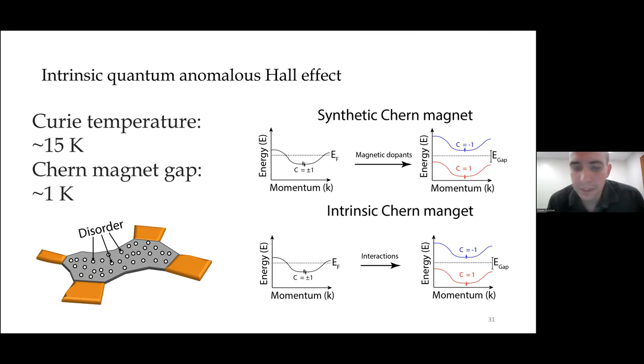And in particular, these doped TIs had the opposite limit from the one I just described. They had a situation in which the Curie temperature was very high, indicating that magnetism was very robust, but the Chern magnet gap was very low, only a couple of Kelvin, which indicates that the local disorder potential was very strong relative to the gap. So the other way to realize a Chern insulator is one in which a pair of Chern bands doesn't depend on magnetic dopants to realize magnetism. It's one in which exchange interactions themselves gap out one of the Chern bands.